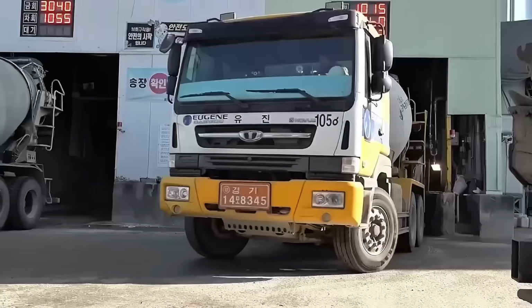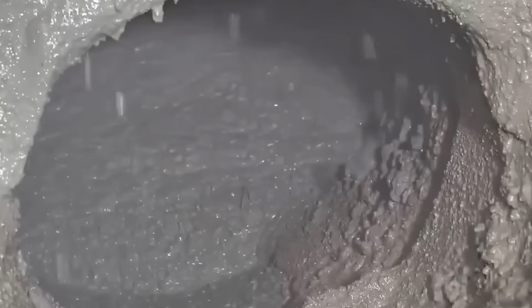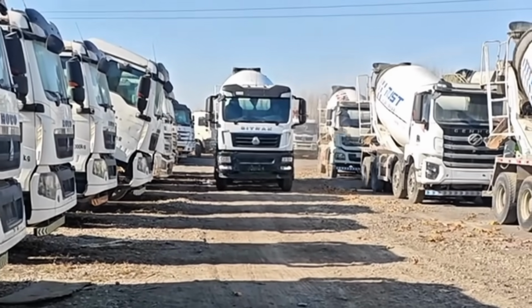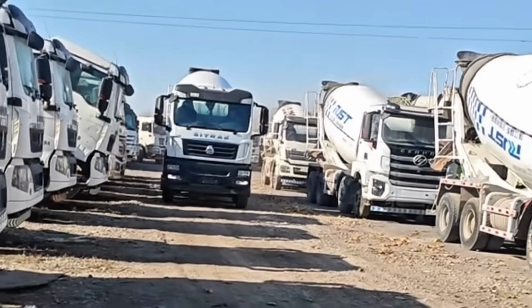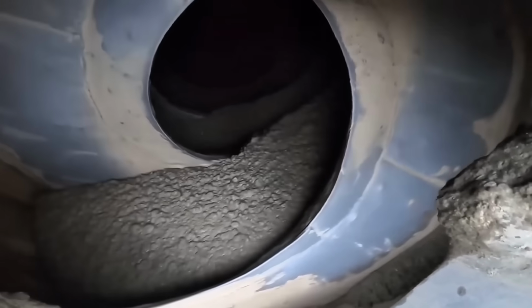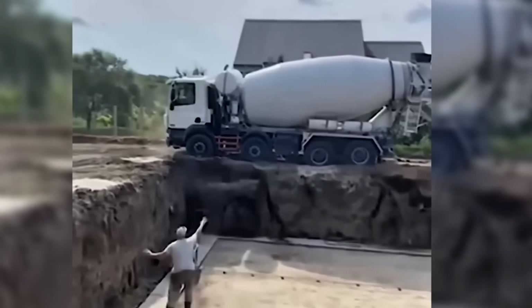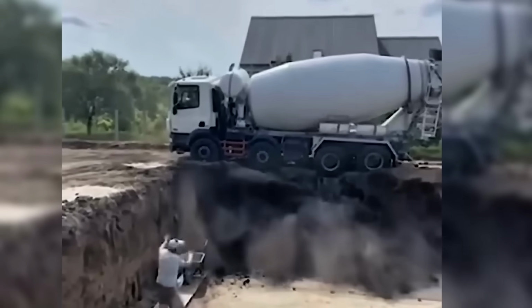It is vital to remember, the drum should never be filled to the brim. There are 2 reasons. First, the immense weight. The density of wet concrete is about 2.4 to 2.5 tons per cubic meter. A drum with a standard geometric volume of 12 to 14 cubes can physically carry no more than 8 to 10 cubes of mix. Otherwise, the total mass will exceed the allowable loads on the axles and bridges.